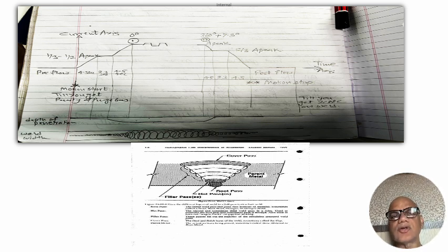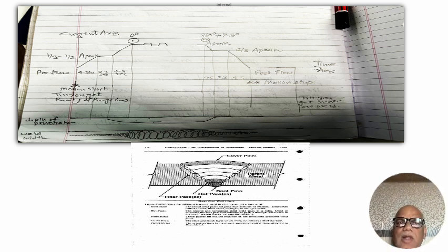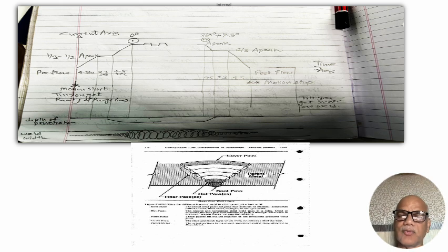Now your actual overlap will start, that is 7 to 8 degrees of overlap at the same current, the full current. And then you stop your full current and start descending down on your curve to the next level of current, which is normally 2/3. And at this 2/3 current you try to fill up your crater and avoid crater cracks.